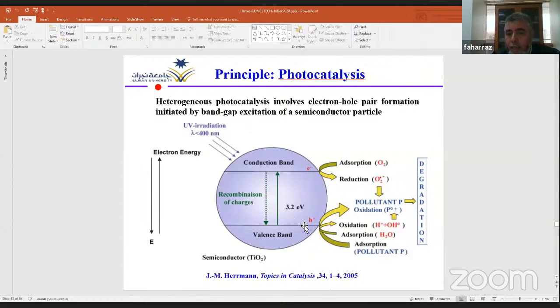The holes stay as the valence band of titania semiconductor, whereas the electrons are excited to the conduction band. The electrons can participate in the reduction process, reducing dissolved oxygen to produce very active oxygen radical species. Whereas the holes are very active oxidants, used to oxidize water to produce hydroxyl radical. Both these active radicals can participate in photodegradation of the target analyte or organic pollutant.